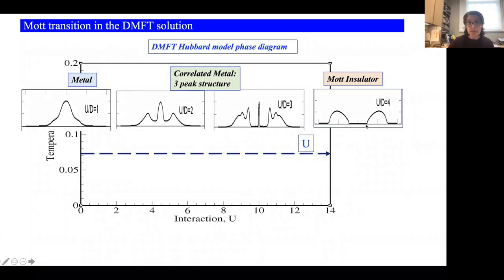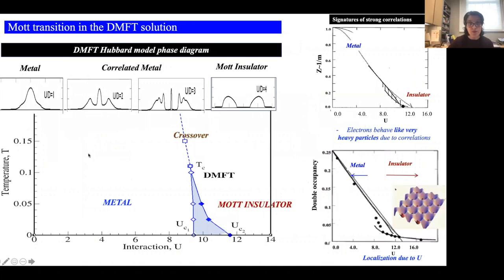One, of course, can do this analysis for other temperatures and construct the full temperature-U phase diagram, where for small interaction U, you have a metal, and for large interaction, you have a Mott insulator. In between, you have this first order Mott metal-insulator transition, and these lines delineate the coexistence region of this transition. The first order transition, as expected, ends at a second order continuous transition with a critical temperature TC, above which you have a crossover, right?